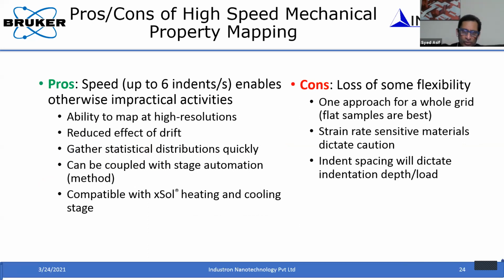Second, because you're doing it at a very fast rate, the low frequency thermal drift problem won't come. But still, it's very important to understand that you're doing it at a much faster rate. You're not controlling the strain rate. You're controlling only the loading rate. So you have to mention what rates you're using when you publish the result, because material may respond differently for the different loading rate. So the rate response is very important.